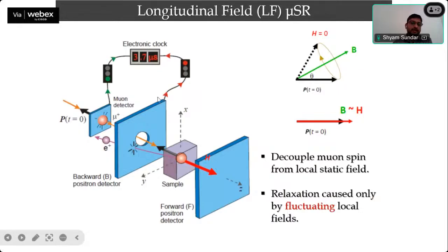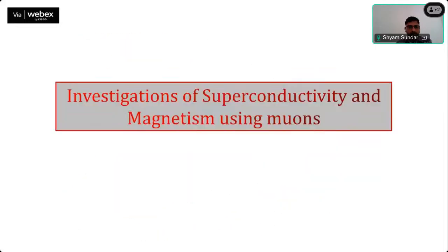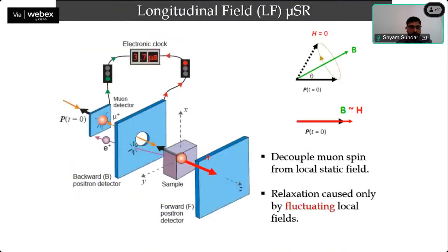There are different configurations in which we can do these measurements. Sorry, I missed the zero field, I guess. So basically, this is the longitudinal field, which means we can apply the magnetic field in the same direction as the muon beam. But this experiment can also be done in zero field, without applying any magnetic field, so that you can detect the local field at the muons in the sample without applying any magnetic field.